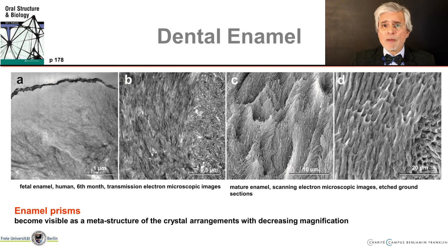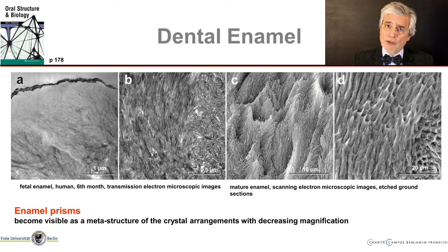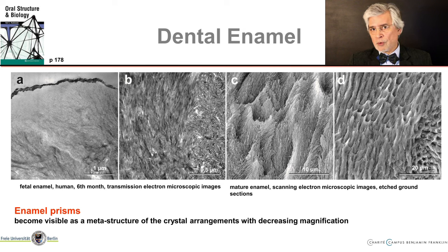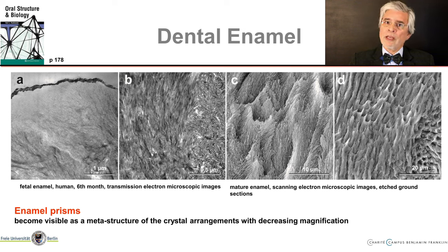At C, we see the crystallites in a scanning electron microscopical image. The specimen was first ground smooth and then etched for 30 seconds with 35% phosphoric acid. We can see structures in two orders of magnitude: the small structures are the crystals arranged in the shape of needles. If you squint your eyes a little bit, you can see a coarser structure, which is also recognizable in the rightmost image at D. This is the same specimen from a slightly greater distance — what you see now are the enamel prisms. Each ameloblast leaves the enamel matrix underneath it, with crystals arranged lengthwise in the center and more obliquely or transversely at the edge. These enamel prisms are thus recognizable as the meta-structure of the arrangement of the crystals — the enamel prisms are the petrified image of the ameloblast movements.